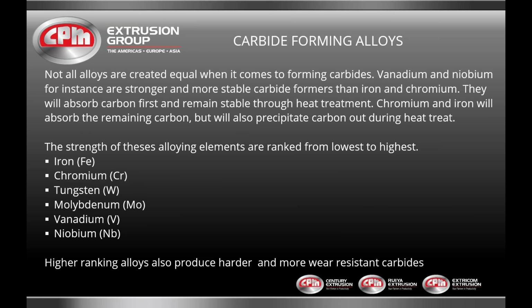Not all alloys are created equal when it comes to forming carbides. Vanadium and niobium, for instance, are stronger and more stable carbide formers than iron and chromium. They'll absorb the carbon first and remain stable through heat treat. Chromium and iron will absorb the remaining carbon, but will also precipitate carbon out during the heat treat process. The strength of these alloy elements are ranked from lowest to highest, with iron being the lowest and niobium and vanadium being the highest. The higher ranking alloys also produce harder carbides that are more resistant to wear.